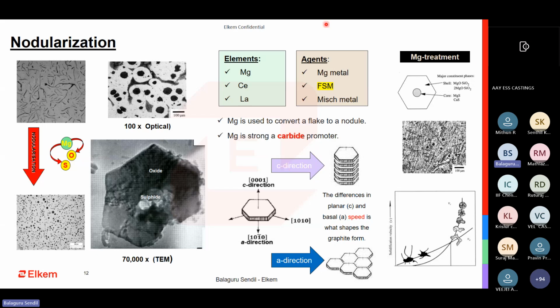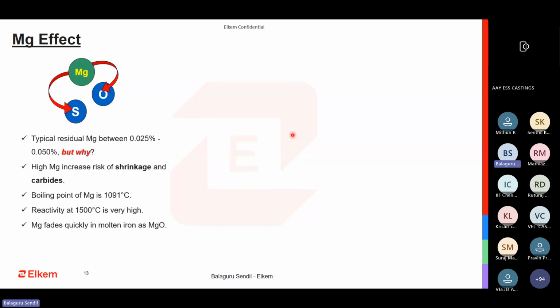So in this slide, the key point here is that magnesium is a good element to convert a flake to a nodule, but it is a very strong carbide promoter and a very strong shrinkage promoter. So we should keep it to the bare minimum possible. In this one, I'm going to talk exclusively about the role of magnesium here. How do I keep this in the nodularization process?